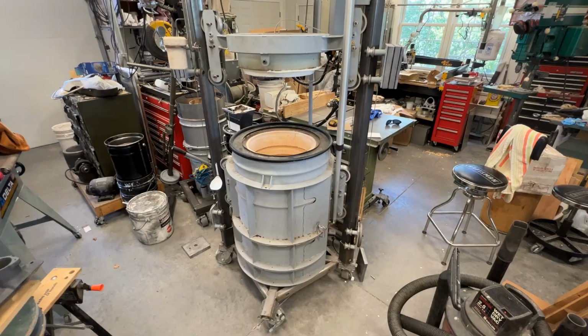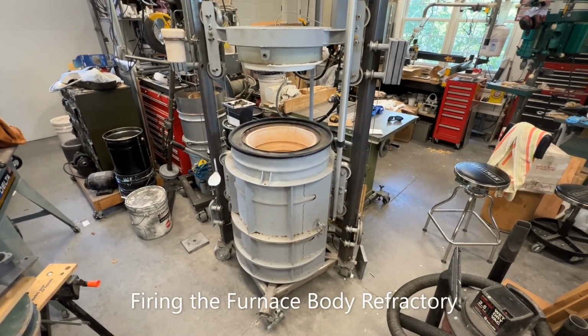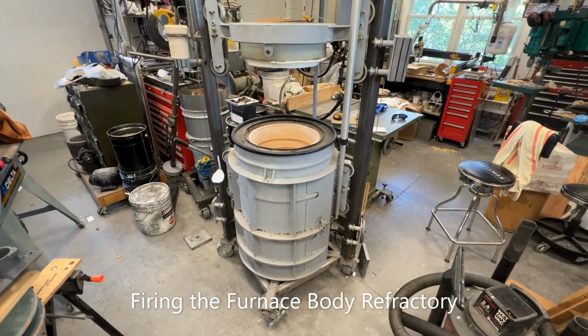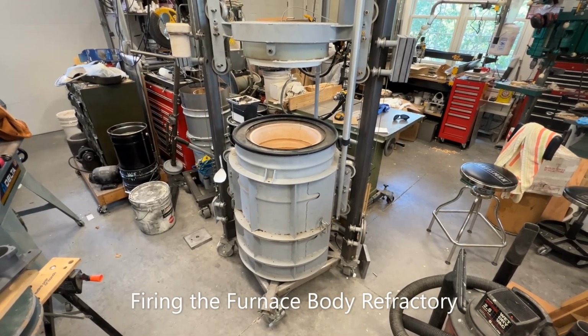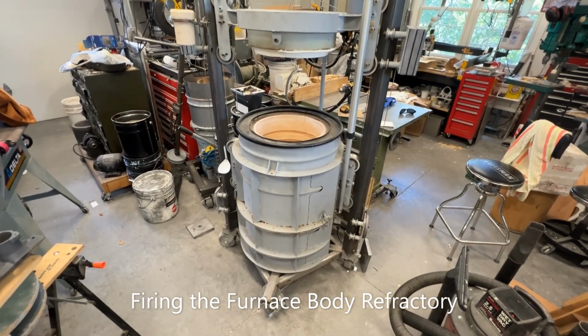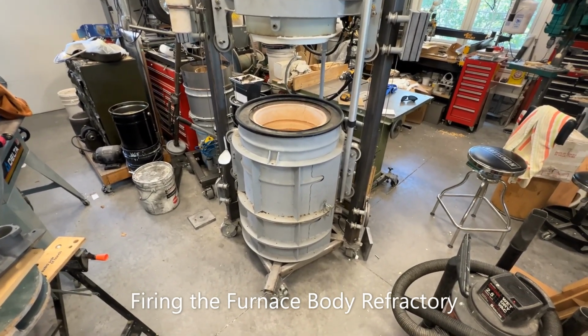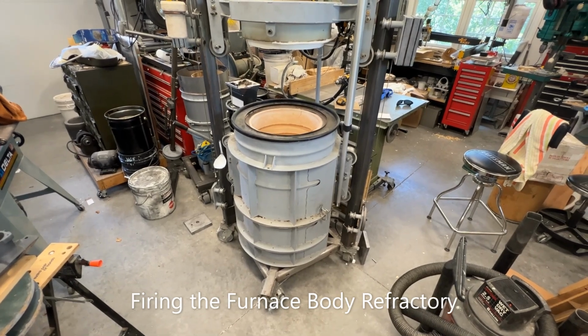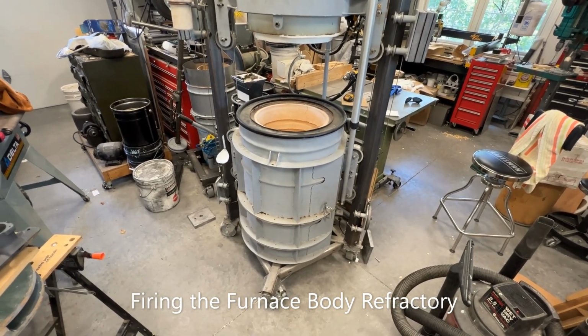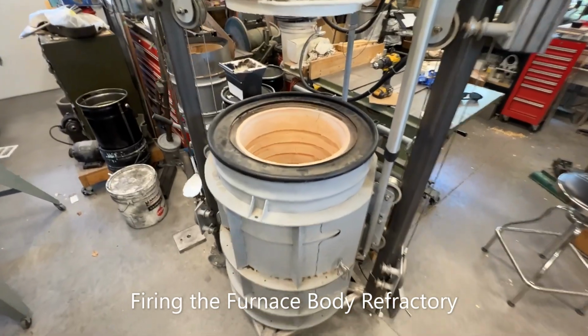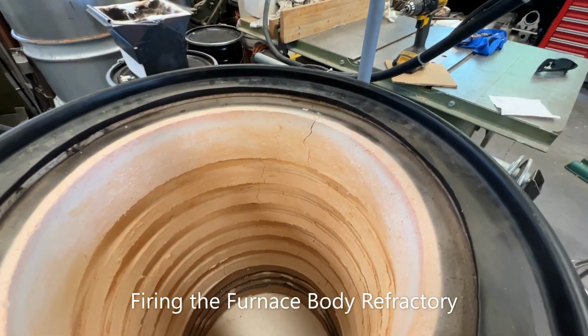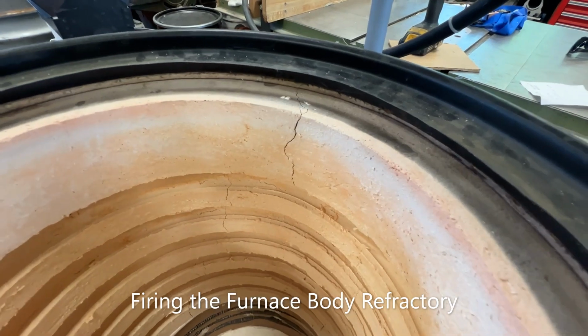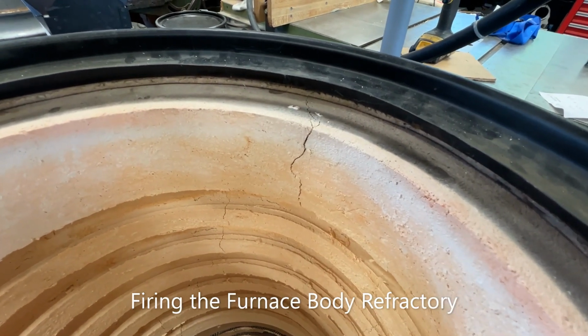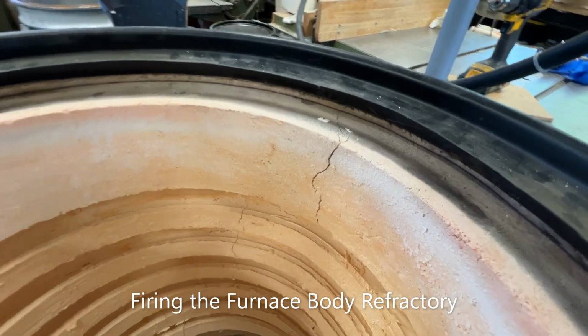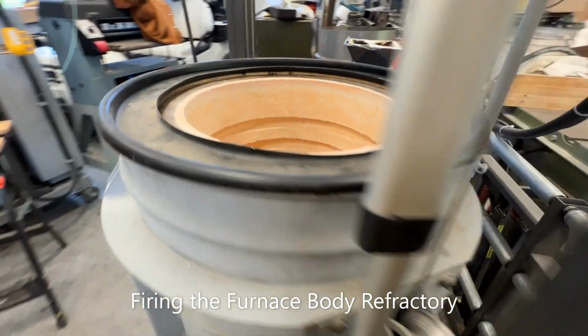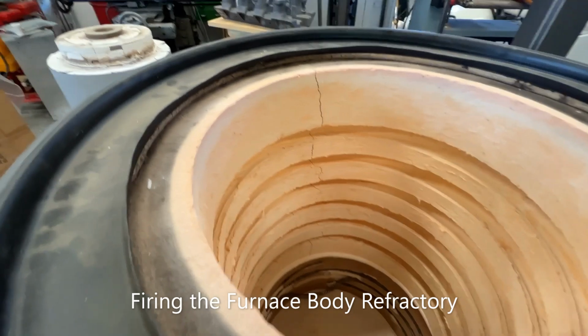Stay tuned. All right, well, I did that swap, and then I took about a whole day to ramp the temperature up to 2000 degrees Fahrenheit to cure that moldable ceramic refractory, and to burn out the styrofoam coil shelves in the midsection of the furnace. And let's take a look at what we've got. While it was hot, there weren't any cracks, but when it cooled down, I did get a couple of pretty significant cracks. One there at the top, which is where it's the thickest, and perhaps the worst one is just opposite of that here on the other side.